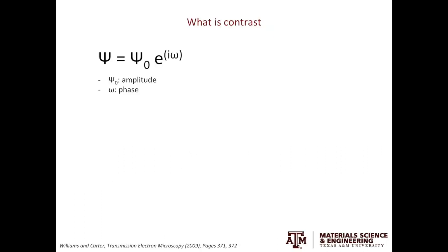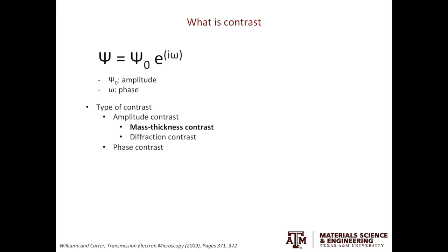When we think about image formation from the electron beam, we treat the electron beam as plane waves. We need just two parameters to define any wave: amplitude and phase. If from one pixel to another there is a difference in the amplitude or the phase of the wave, we will see contrast. From the contrast, we interpret the microstructural information. If the contrast is caused by a difference in amplitude, it is called amplitude contrast. If it is caused by a difference in phase, that gives rise to phase contrast.